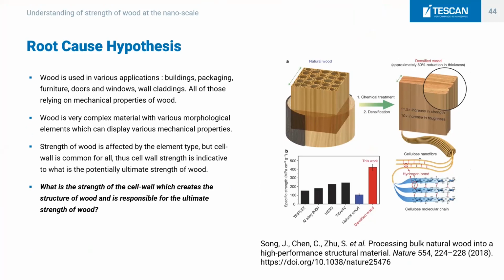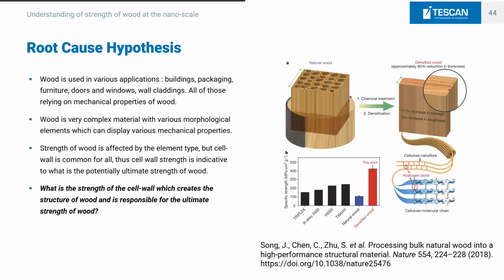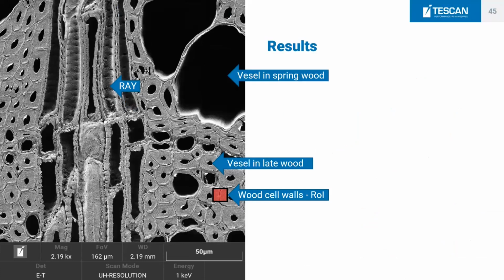Something like that has been tried for many years and published across different papers: if you compress the wood and get rid of the porosity, and you are able to chemically fix the material so that the porosity will not occur anymore, you would get the ultimate strength of the wood. But what is really the strength of the cell wall, which creates the structure of the wood and is responsible for its ultimate strength? That's something we tried to do in one case. So you have a material like this, where you can clearly see the vessel in spring wood, the cell wall, and the ray. And we are interested in the wood cell wall.